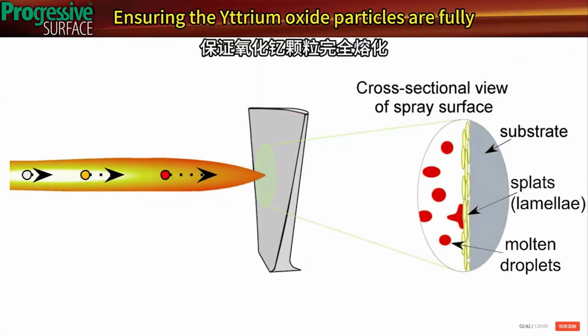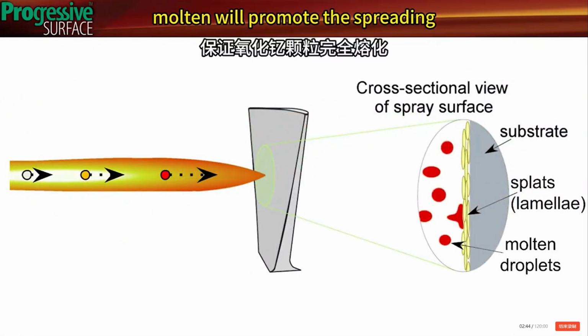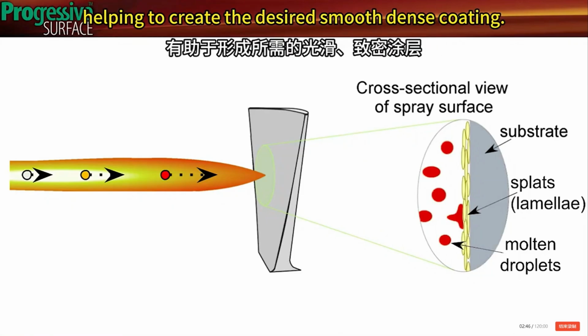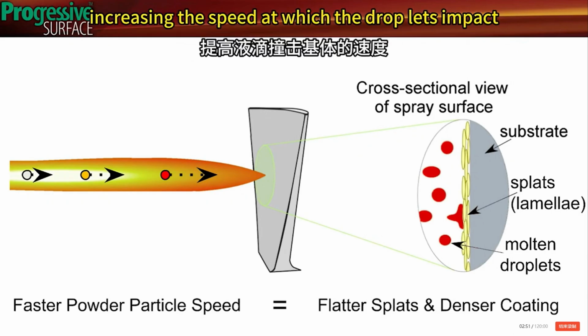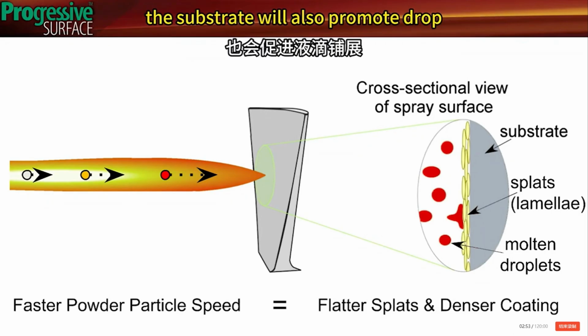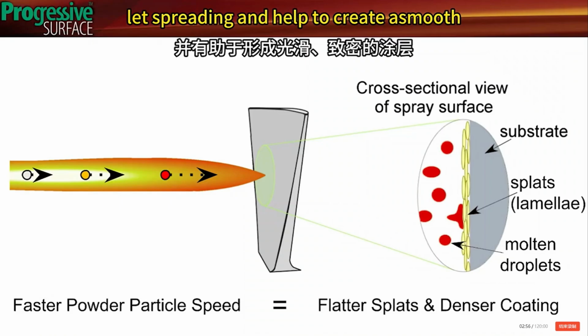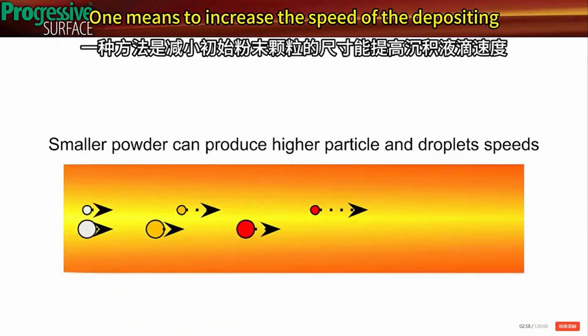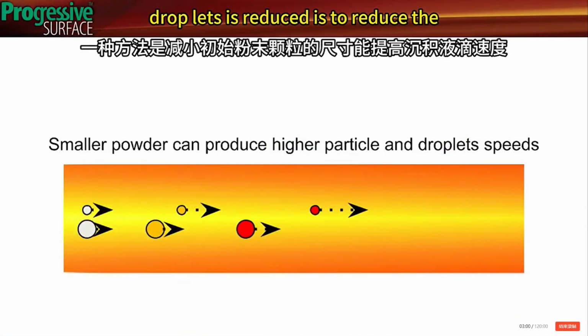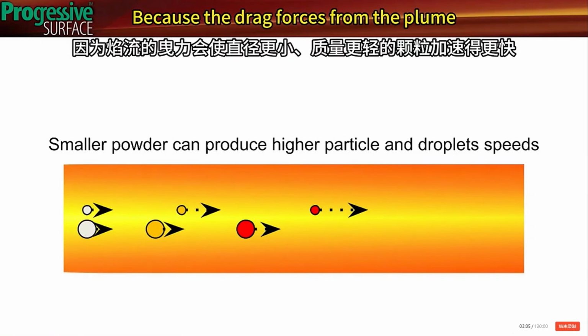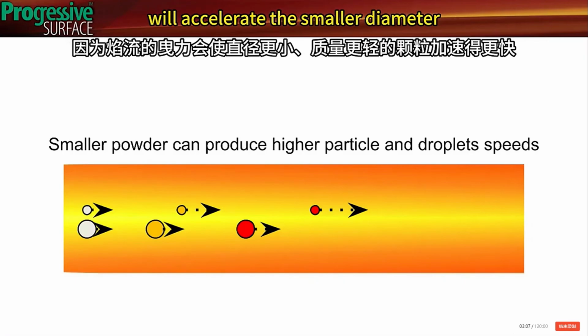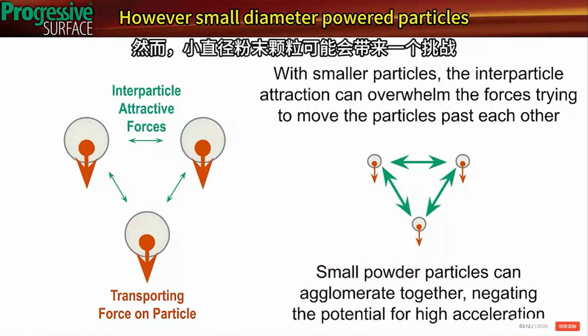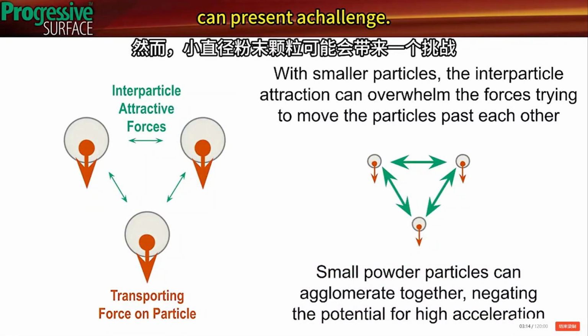Ensuring the yttrium oxide particles are fully molten will promote the spreading of the droplets during impact, helping to create the desired smooth, dense coating. Additionally, increasing the speed at which the droplets impact the substrate will also promote droplet spreading and help to create a smooth, dense coating. One means to increase the speed of the depositing droplets is to reduce the size of the initial powder particles, because the drag forces from the plume will accelerate the smaller diameter, lower mass particles more quickly. However, small diameter powder particles can present a challenge.